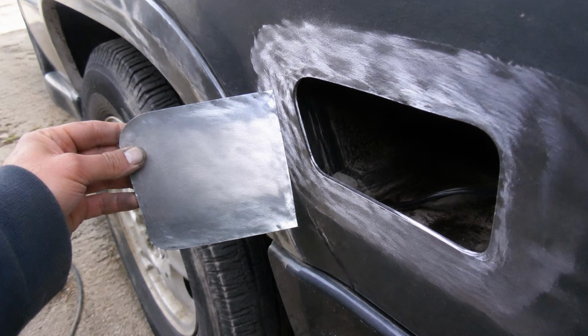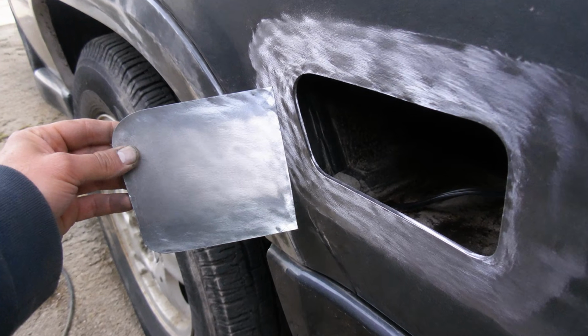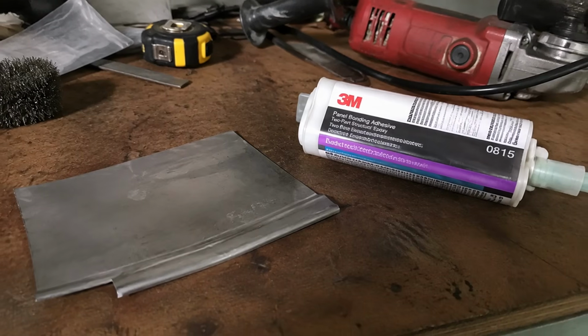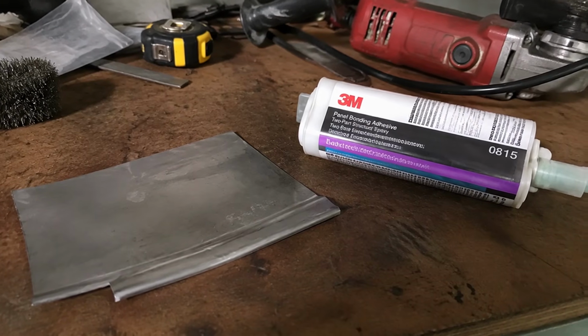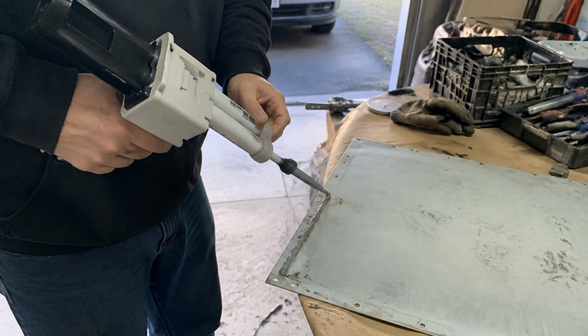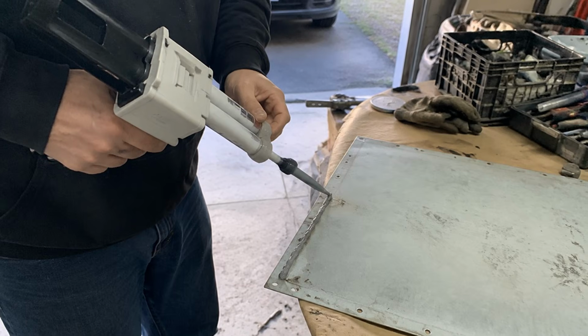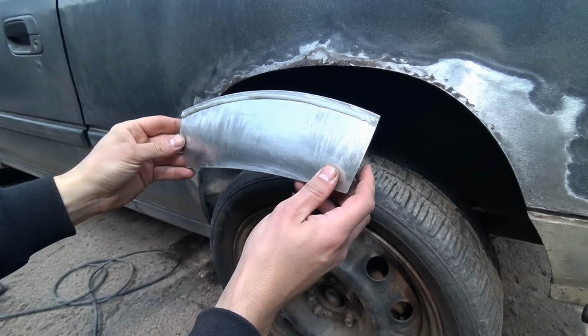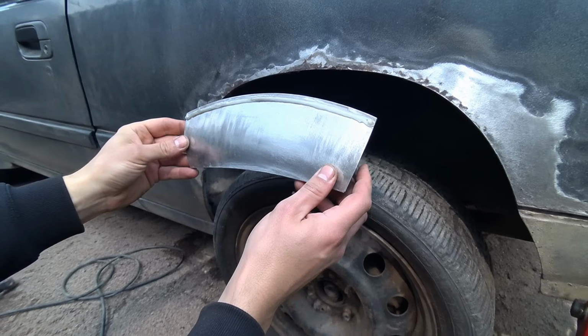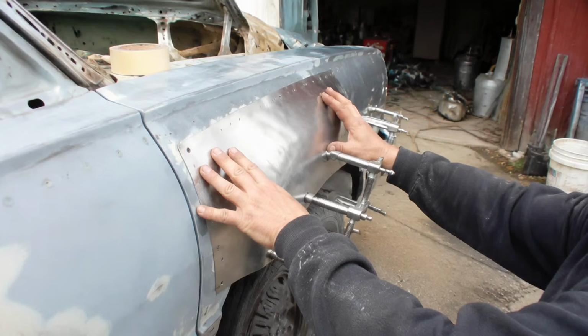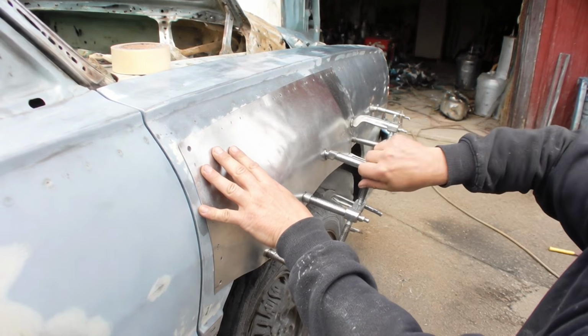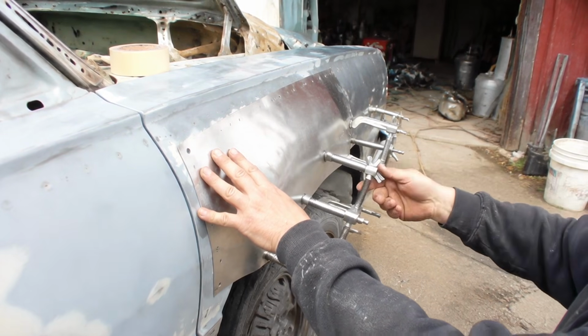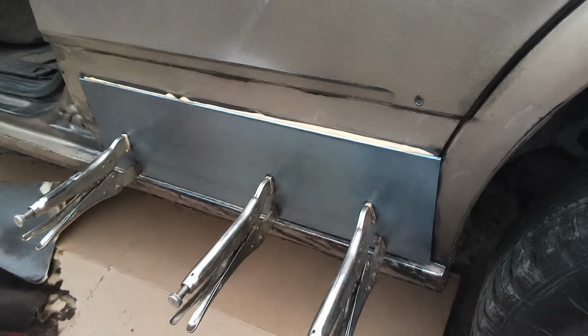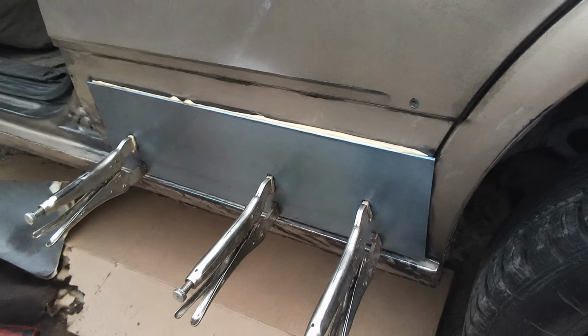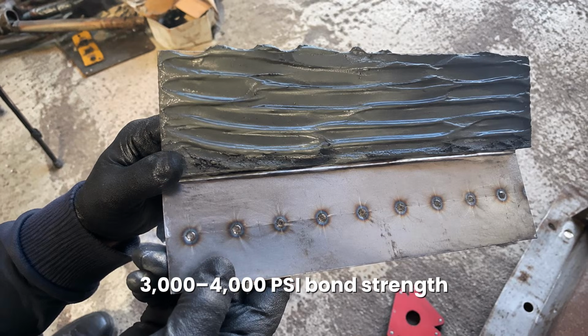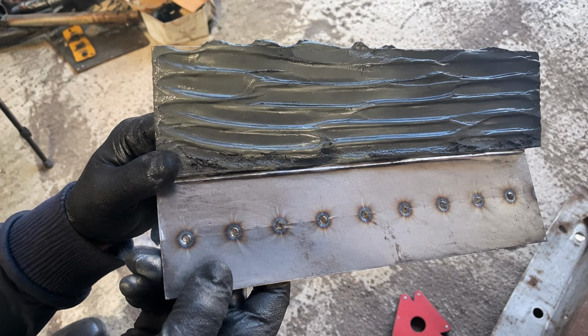The second way, if you want metal behind it, is a patch panel bonded in with adhesive. And this is the part that surprises people, so listen close. There's a product called panel bonding adhesive. It's a 2-part structural epoxy. You cut a piece of sheet metal to cover the hole, scuff both surfaces down to bright metal, lay a bead of the adhesive along the seam, and clamp or rivet the patch in place. When it cures, that bond has a shear strength somewhere in the range of 3,000 to 4,000 pounds per square inch.